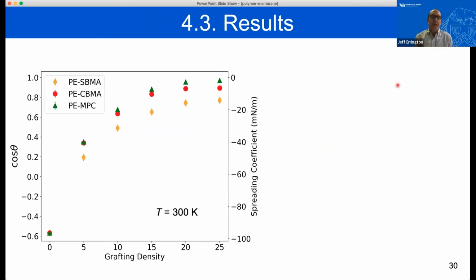All right, so this is an example of the type of results that we get. So we go through a process that's similar to the one that I outlined before. The nuance is that we now have this additional sort of charge expanded ensemble component associated with it. But in the end, these are the results that we get for the cosine of the contact angle, in this case, at 300 Kelvin for systems with various different grafting densities. And again, we're capturing the results for different types of polymer tethers in this case.